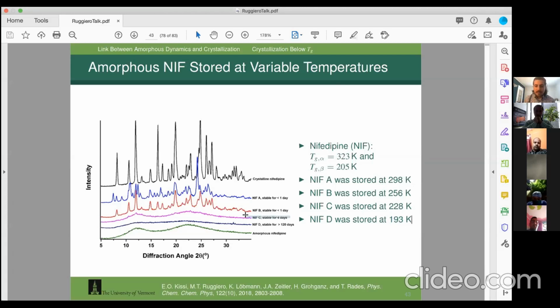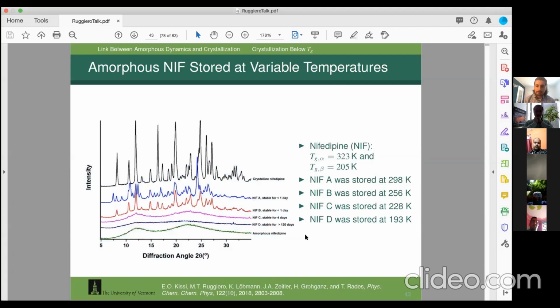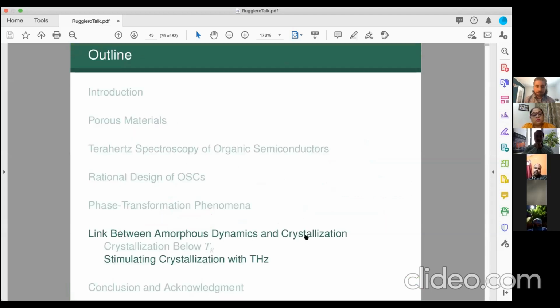Sample C was stable for 4 days by X-ray diffraction before it started showing crystalline peaks. Sample D, stored just slightly below the beta transition, was stable for—when we made this figure, it was 120 days. By the time the postdoc who was doing this left, it was like 2 years, I think. So stable for a really long time.